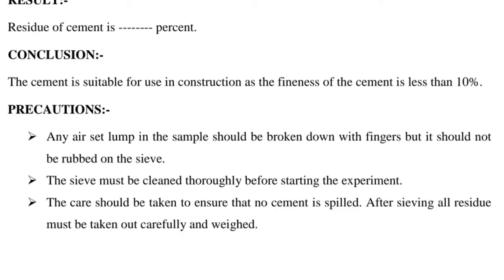Precautions: First, any air-set lumps in the sample should be broken down with fingers but should not be rubbed on the sieve. Second, the sieve must be cleaned thoroughly before starting the experiment. Third, care should be taken to ensure that no cement is spilled. After sieving, all residue must be taken out carefully and weighed.